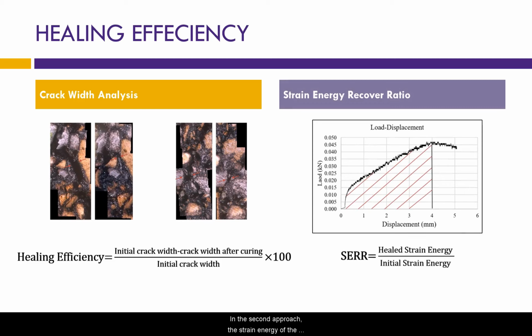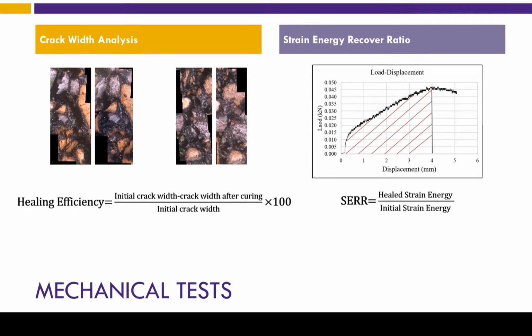In the second approach, the strain energy of samples, which is defined as the area under the load displacement curve up to the peak load, is measured in two states. One, when the crack was induced, or initial strain energy, and two, after 6 days of healing, or healed strain energy. Strain energy recovery ratio is calculated as the healed strain energy divided by the initial strain energy.